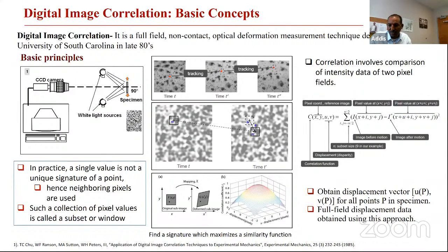You have a specimen that is speckled in a pattern. In this case, it's white and black dots. The specimen is under loading, and you take an image starting from a reference image before the load happened, and subsequently take images while loading. Then you can track each point or position to find displacement. Once you find displacement, you can calculate strain and other conditions.